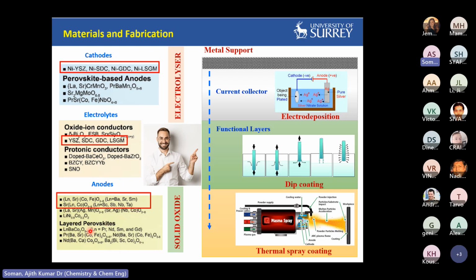And for the anodes, most of the layered perovskites are the best oxygen oxidizing materials, so you can easily transform the oxide species into pure oxygen. So these are the materials we are working on. And in terms of the fabrication, this is how we design. We come up with the deposition method of electrodeposited silver. So we are fabricating the silver as a current collector by electrodeposition onto the metal support, and the functional layers, all the ceramic layers, the cathodes, electrolytes, and anodes, are fabricated by cost-effective dip coating. And of course, we went with the thermal spray in the optimum thickness. So this is our overall approach for the fabrication.